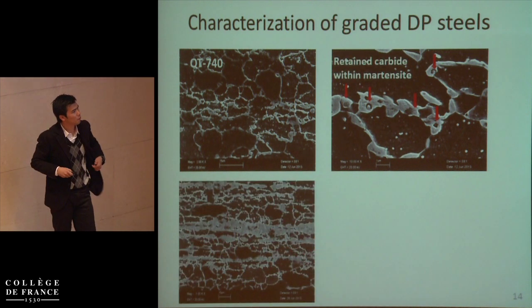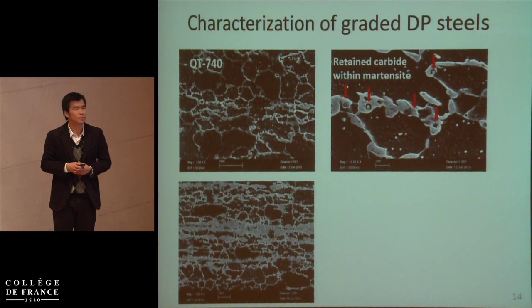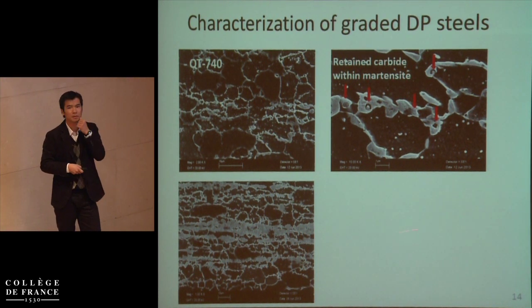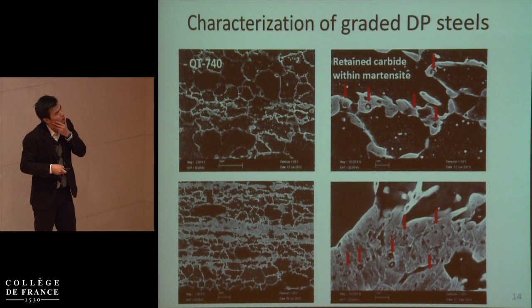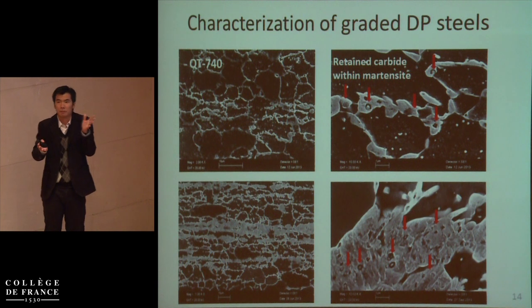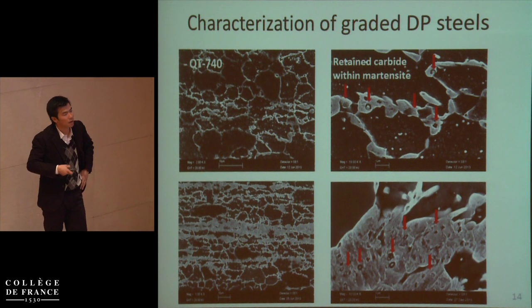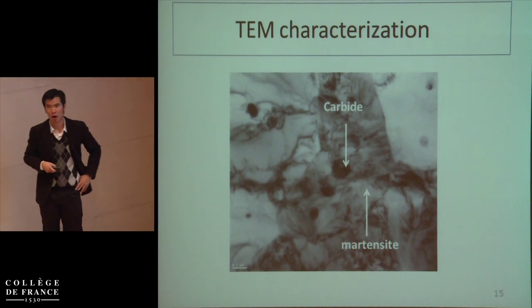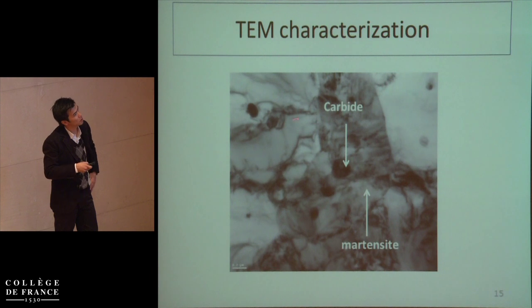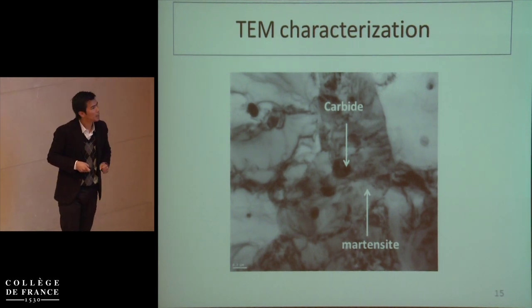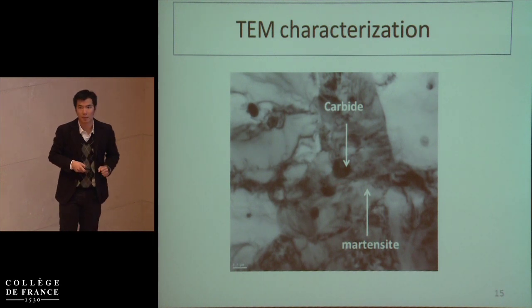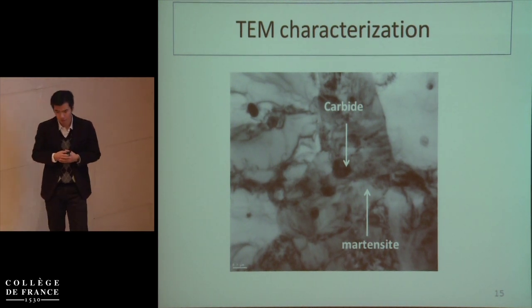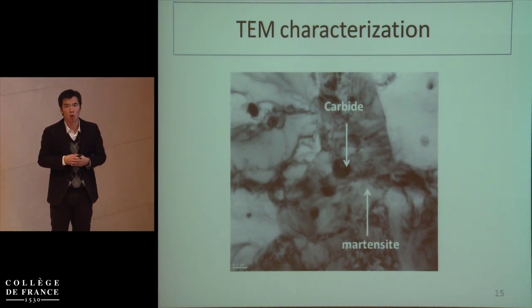For the microstructure with more volume fraction of martensite — about 35% — due to the relatively high manganese content the banded structure is very obvious. With high magnification we can see that even with a larger martensite content there are still a lot of carbides within the martensite. Under TEM we can see the core-shell architecture more clearly: the ferrite matrix, carbides within ferrite transformed to austenite, and the martensite island with carbide particles. Occasionally there is more than one carbide within a single martensite island. So far it is believed there is enough proof that we have fabricated the core-shell architecture.